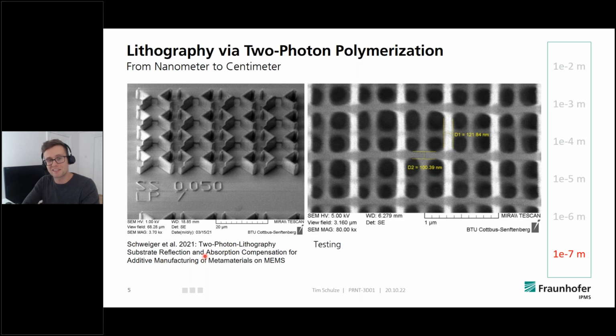So the idea with the following slides is to give you an idea of the scale we can print structures. So here you see the scale from several hundred nanometers up to centimeters. And if we start with the really, really small things, we can see here test structures. Here was a single voxel line in the middle of those triangles, and it was just to find out how the printed line behaves in different distances compared to the substrate.